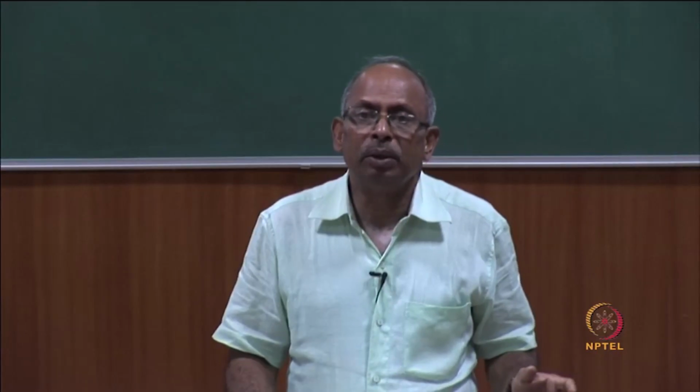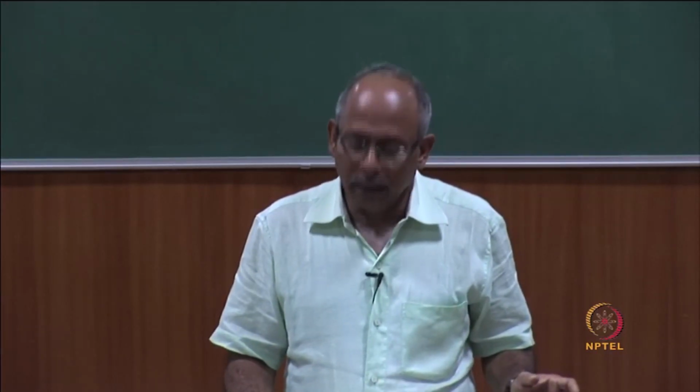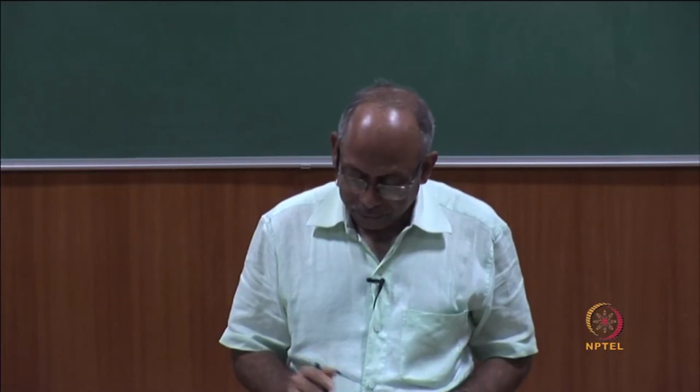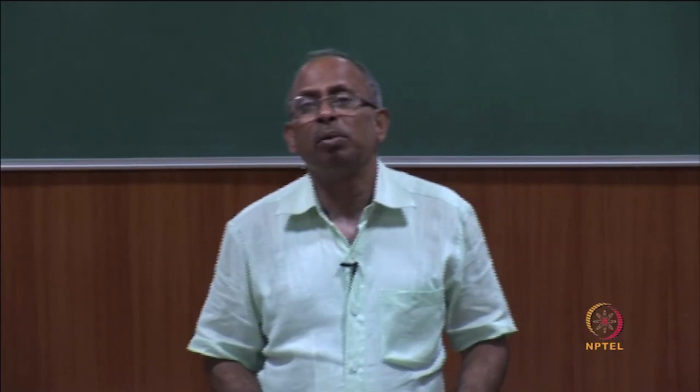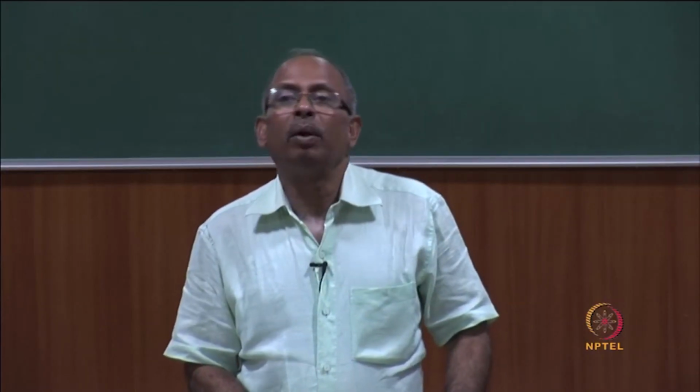It has a tendency to flatten out in the long run. All right. So, this is time and relative humidity. If it is fully saturated, there could be swelling. If the relative humidity is very high, close to 100% or just 90% or so, shrinkage will be very little, but it is all related to drying.